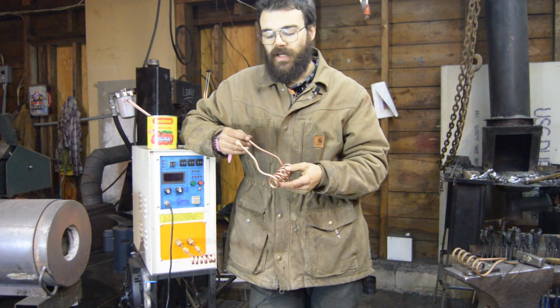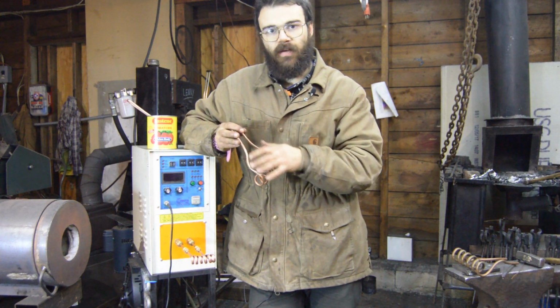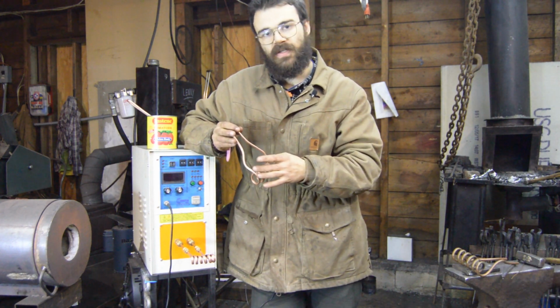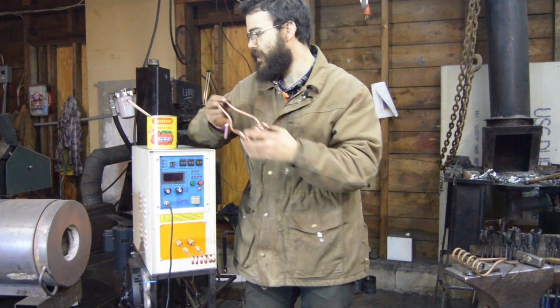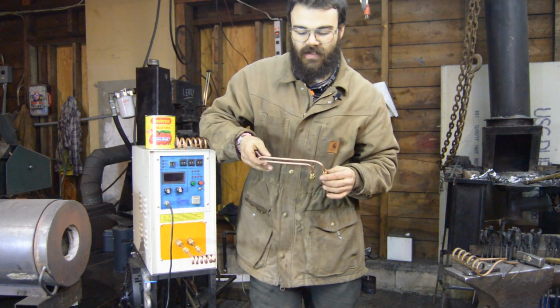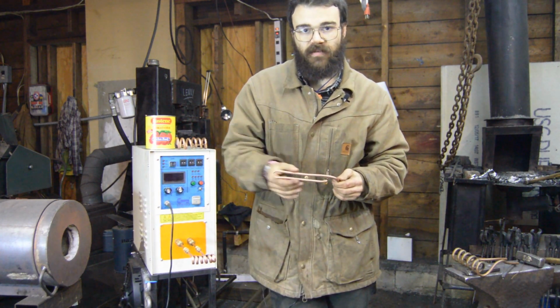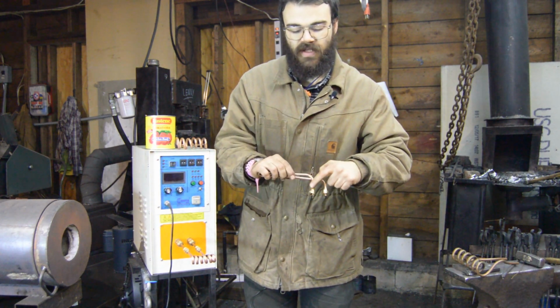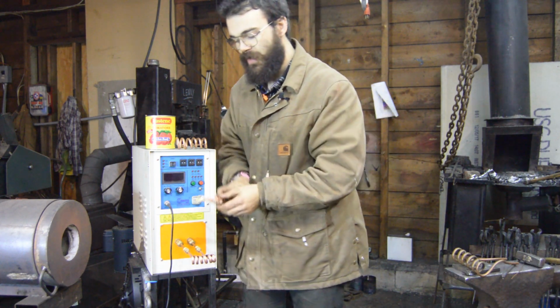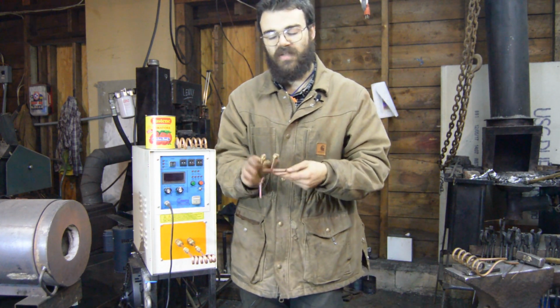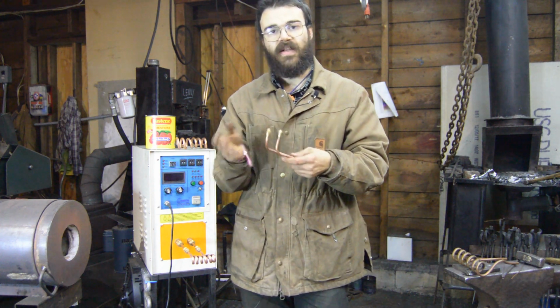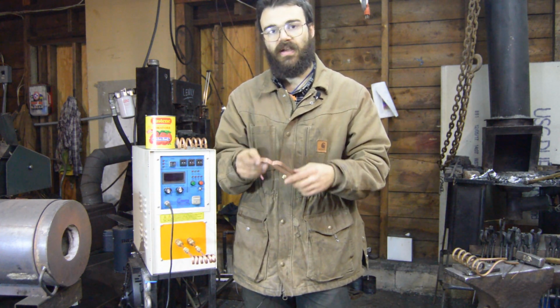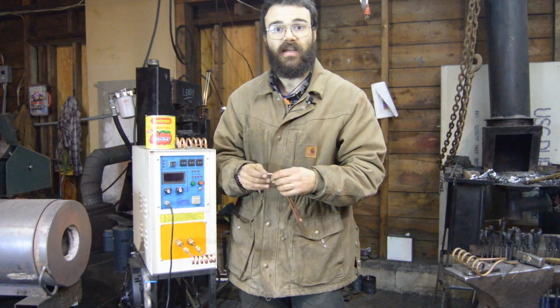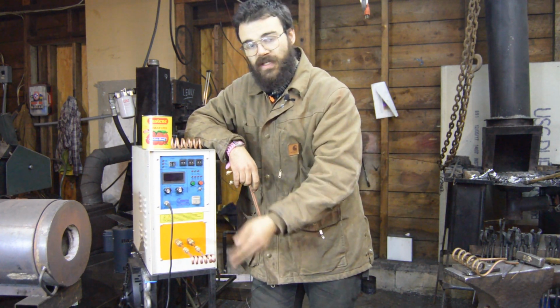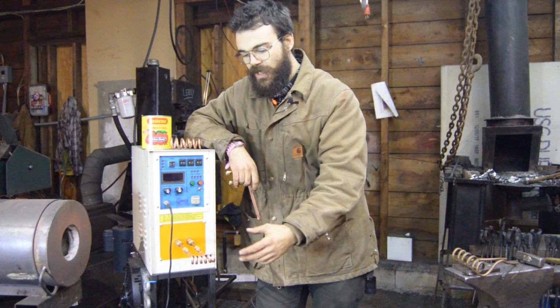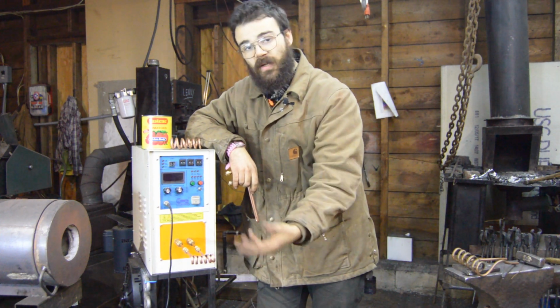One more important consideration is to keep these excess pieces of tubing as short as possible and as close to the coil as possible. This is actually a pretty bad spacing right here. But if you look at this, this is where the main heat is being applied. So these extra pieces of tubing, just to get the liquid back to the heater, are kept as short as possible and as close together as possible. And again, that's to prevent the leakage of magnetic flux lines around parts of the coil that aren't even used for heating. Because we're passing current through the entire coil assembly, we're generating most of the magnetic field lines inside the coil just because of how it's arranged.